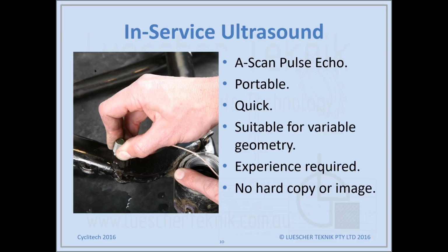Within service ultrasound, we typically use A-scan pulse echo because it's portable, it's quick, and it's very suitable for the variable geometry that you get in a bike frame. Due to all the curved shapes and junctions, it's very difficult to produce a C scan of that type of product. It's also very difficult to do a through transmission because you need access on both sides. If you've got a small diameter tube, you can't get a transducer inside that tube, so you typically use pulse echo A-scan.